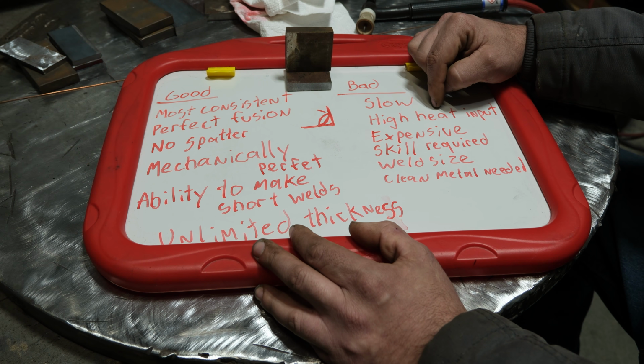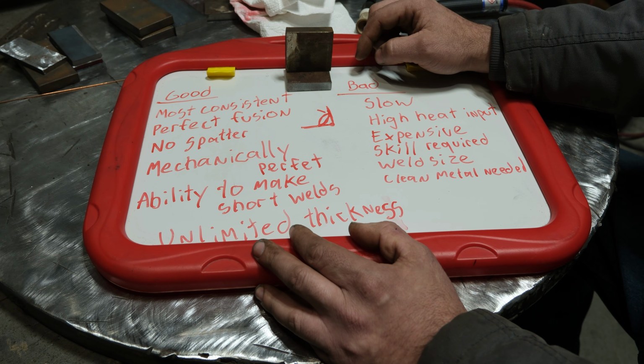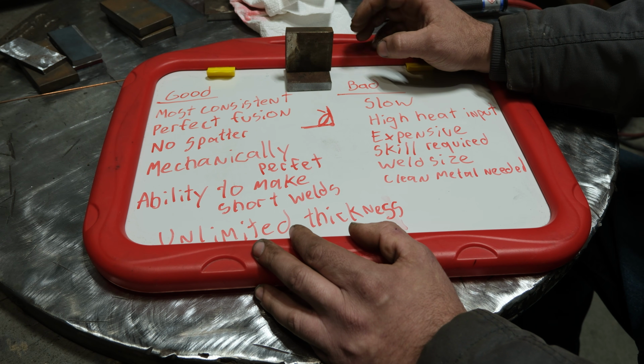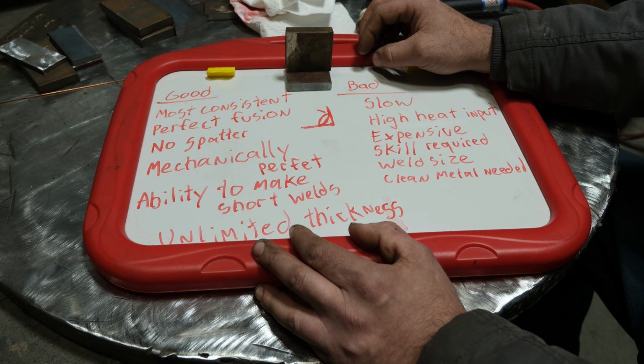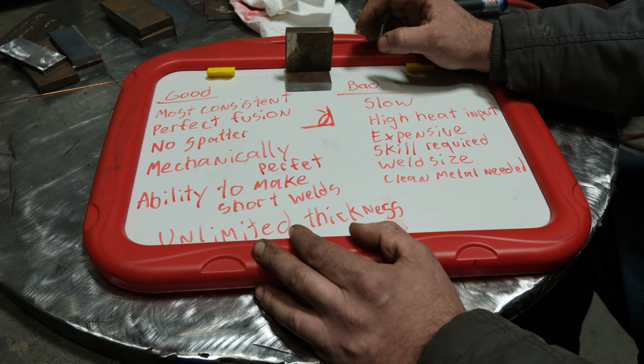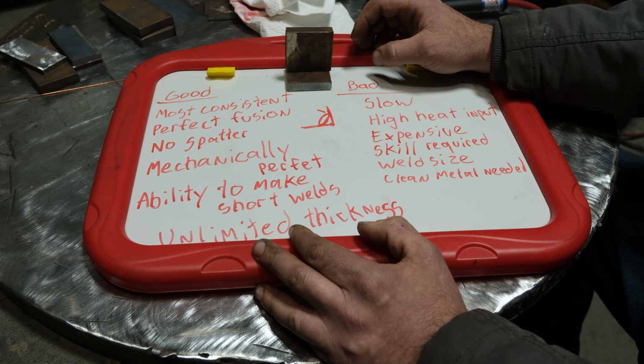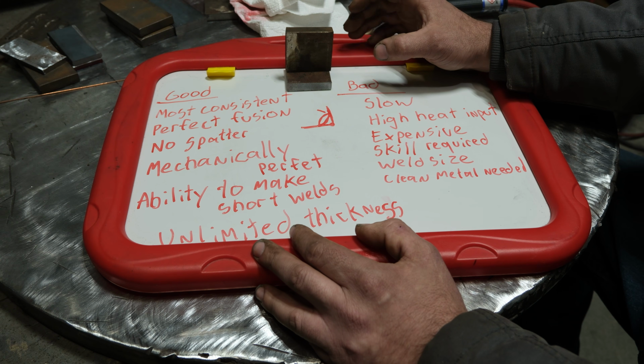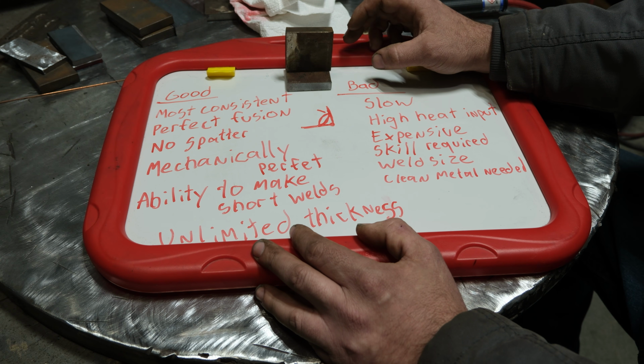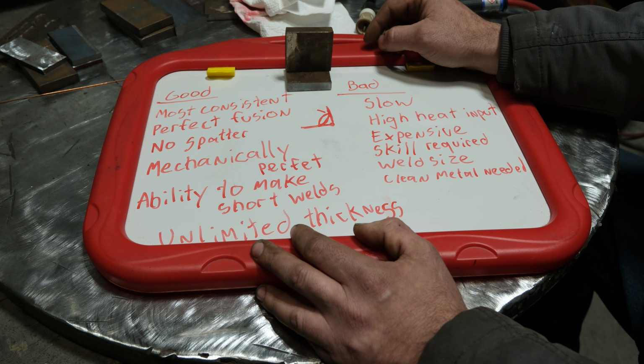Now, this becomes a concern on certain materials, okay? A good example would be cast iron. If you preheat cast iron and then weld it with a nickel rod with stick, odds are you're going to be all right and you're not going to experience too much cracking, okay? As long as you get it hot enough to start and not expedite the cooling, you give it time to cool, right? Well, with TIG, you can TIG weld cast iron.